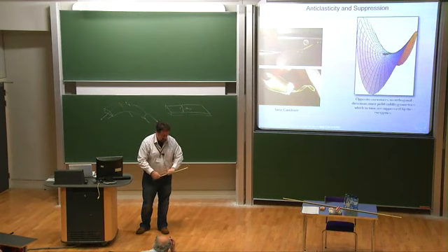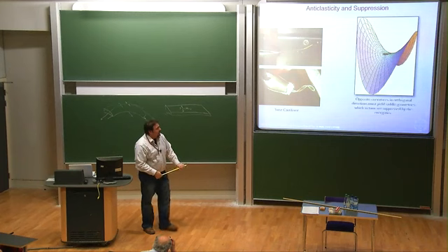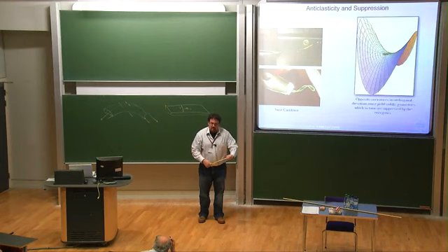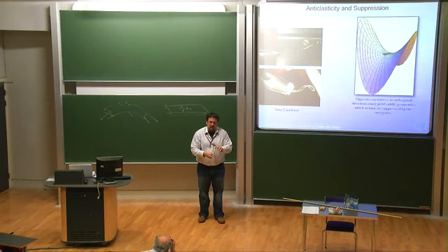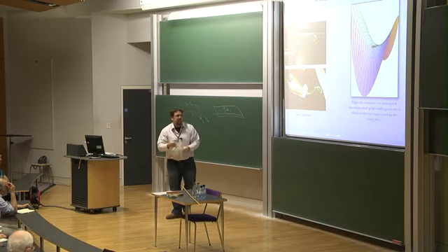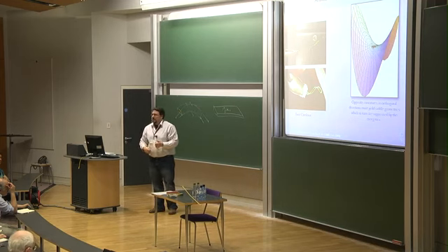And if you try to bend it, if you put a bend in the opposite direction, you would think that you're imposing a bend that would create this sort of shape, with equal and opposite bends. But what happens is that's so strongly suppressed that it snaps through completely, and you get a free mode. There's now no bending at all along the direction that you previously had the bend, and the amount of bending that you get in the new direction is exactly the same as the bending you had in the old direction by the energetics, and it's free. So this is the strength of the suppression. It's a very, very strong energetic suppression that occurs.